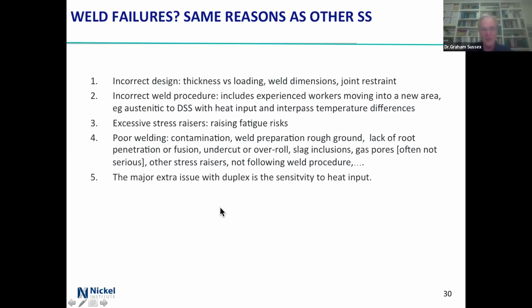The major extra issue with duplex is just the sensitivity of the heat input. Put too much heat in, keep it too hot too long, and you'll muck up the actual solidification and you'll wind up with wrong ferrite austenite ratios.